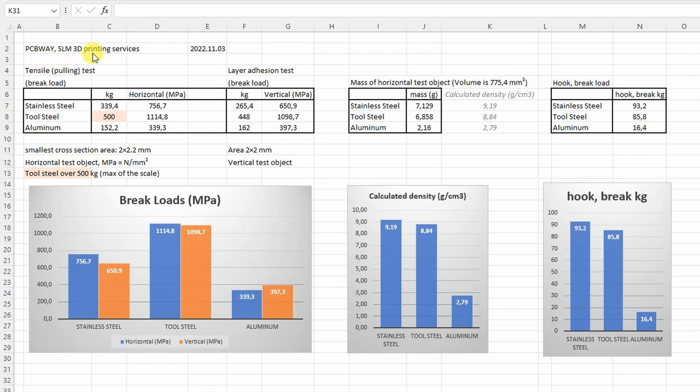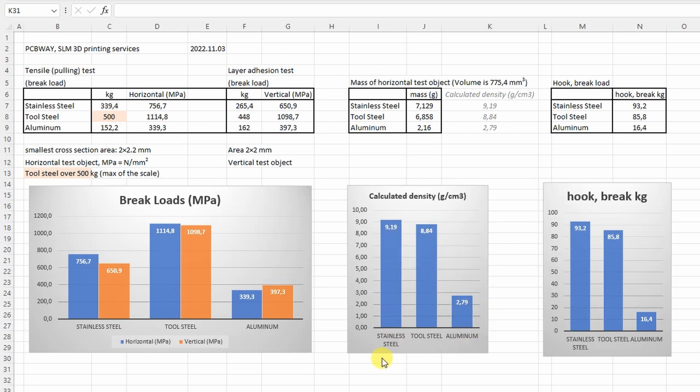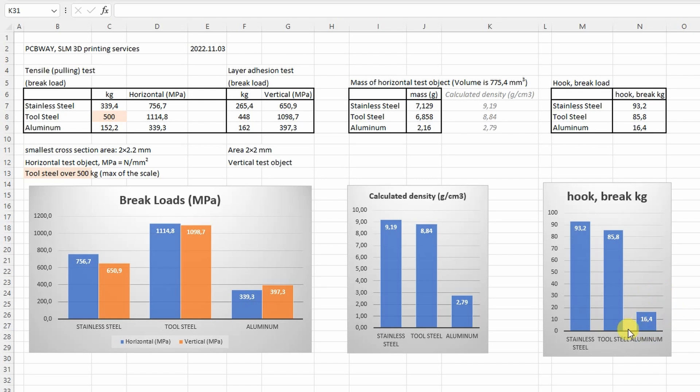Let's analyze quickly the results in this Excel table which is downloadable from mytechfun.com website. Well, maybe for me this is the most important to see that horizontally or vertically printed test objects have very similar strength in all three materials. This is calculated density and it is not really equal. It's a little bit bigger than the real density of the raw materials. The reason for this is that the theoretical and the real volume is not 100% equal. And about this hook test, these are just break loads in kilogram, but what is more important here is the type of the break. As expected, stainless steel just deforms and slips from the testing hook, but the tool steel is a brittle material so it breaks suddenly, but of course it is harder, it is good for manufacturing tools. And this is for aluminum. I wasn't sure for the type of the failure, but it also breaks very suddenly.